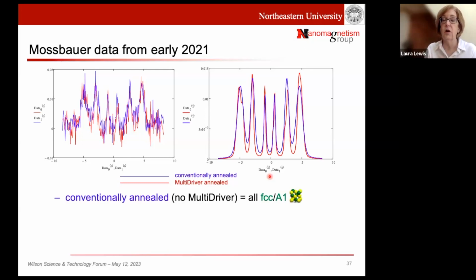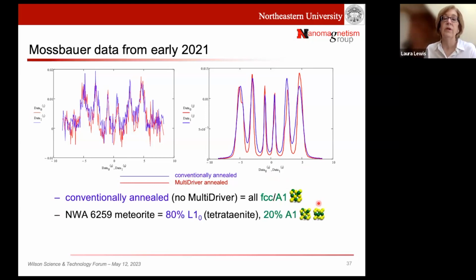And in our conventionally annealed samples that we sent, there was no tetrataenite. Everything was this cubic crystal structure, disordered. We looked at a piece of our meteorite for calibration, and that was 80% tetrataenite and 20% of this disordered phase. And that's to be expected.